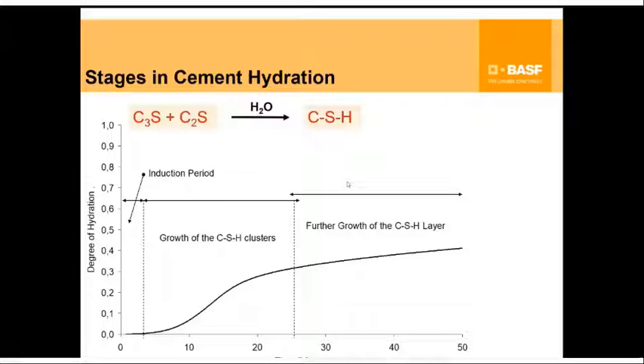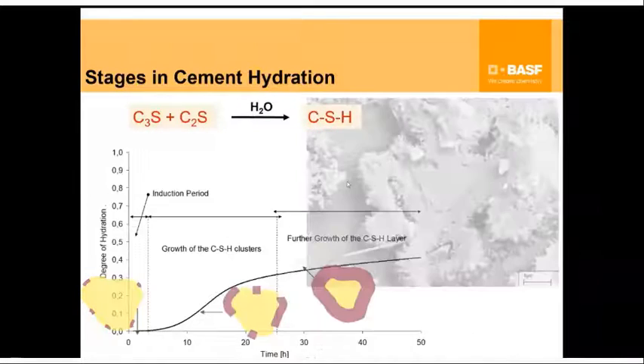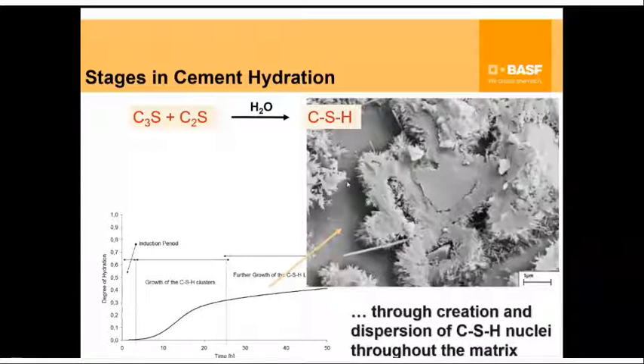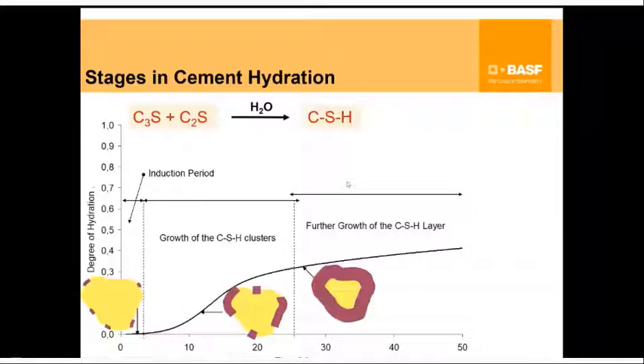Next, Rama. So if you are looking at a cement grain, sorry, if you could go back, Rama. If you look at a cement grain in the initial phase, you will see mostly cement surface, but there will be this small nuclei of CSH shown here in purple, I think. And these are the places where the growth phenomena of CSH starts. And as the hydration continues, these are the points where more and more CSH starts accumulating and growing, and then slowly it grows across the surface, all the way covering the full surface.